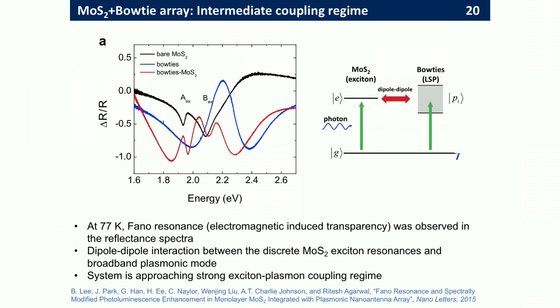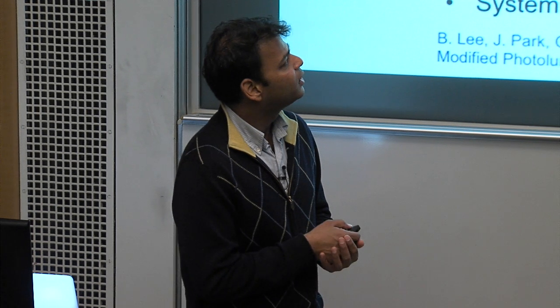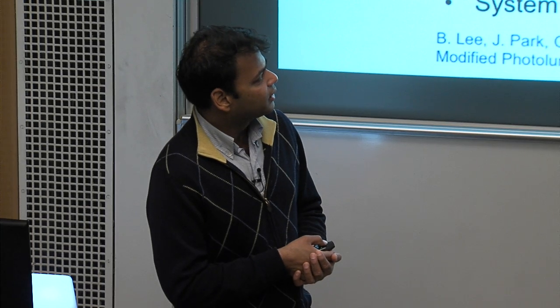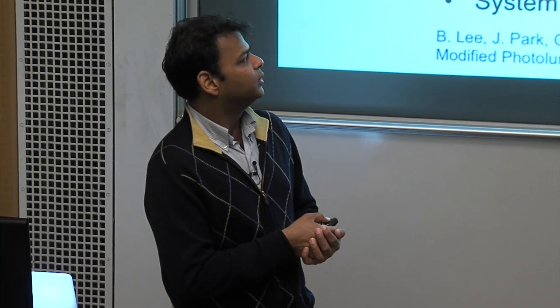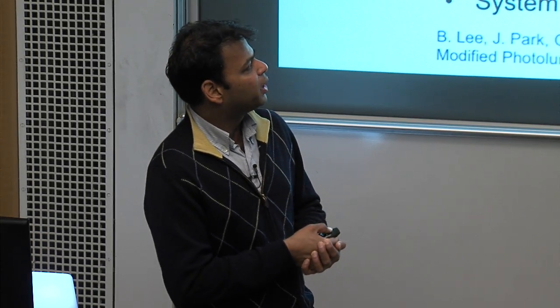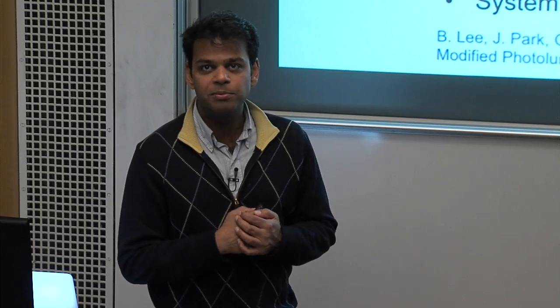But anyway, what happens in a Fano line shape is you have a two-level state which couples to a broad continuum. Here the two-level state is the exciton system, and the broad continuum is the broad plasmonic excitations, the continuous spectrum from the plasmons. If you have relatively strong coupling between the exciton and the plasmon, there are many ways to describe it, but what happens in a Fano system is you have two quantum pathways, and they interfere, which means the initial state and the final state have to be the same. One pathway is the direct excitation of the exciton, and the other is excitation of the plasmons, and via dipole-dipole coupling, you excite the exciton. So you have two pathways, and when they interfere, they produce this asymmetric line shape.